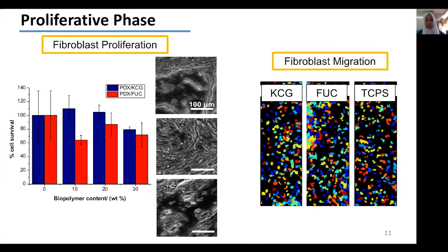And we found that all the samples, therefore the positive control TCPS, the kappa-carrageenan containing scaffold, and the fucoidan containing scaffold, they all favored migration of cells into the wound area. But if we look closely at the three images, we can see that the fucoidan containing scaffold promoted the migration of fibroblasts to a much higher extent compared to the remaining two samples.